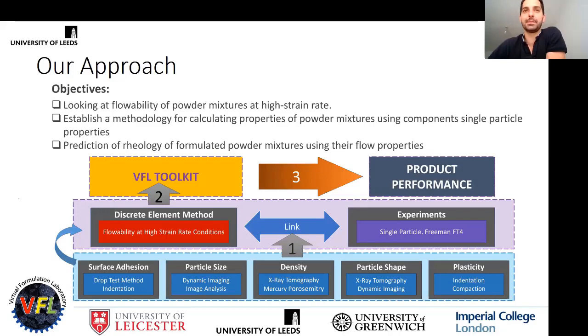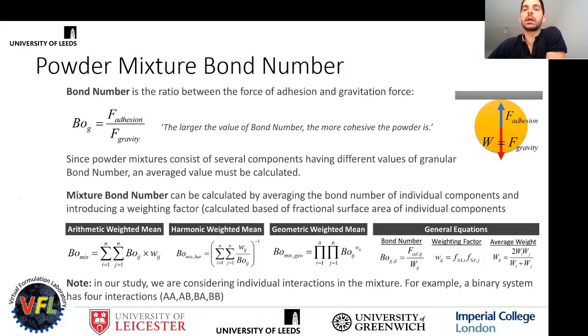So next one. We came up with a methodology to represent the cohesivity of the powder mixtures by bond number, which we call the mixture bond number. And we investigated different methodologies for averaging the bond number. This approach uses the interaction of the components rather than the bond number of each component. So in a binary mixture, we have 4 interactions: component AA, AB, BA, and BB. That is how we are calculating the mixture bond number.